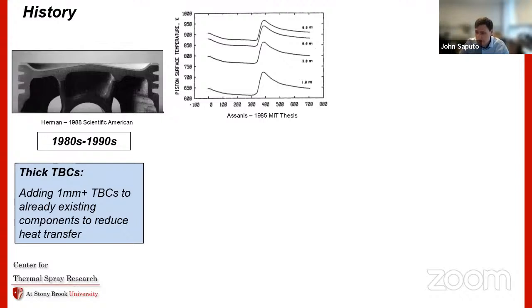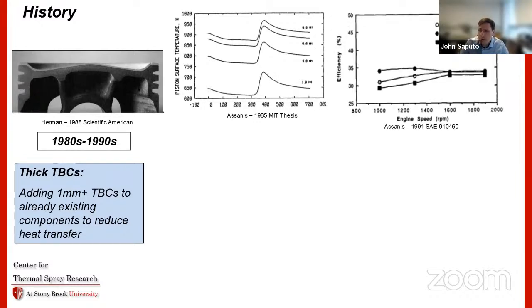And you see that baseline temperature slowly go up and up, which ends up being an issue. So what people predicted was that as the surface temperature of the components get hotter and hotter, you're going to slowly degrade combustion by heating the cool intake gases that come into the system early in the cycle.